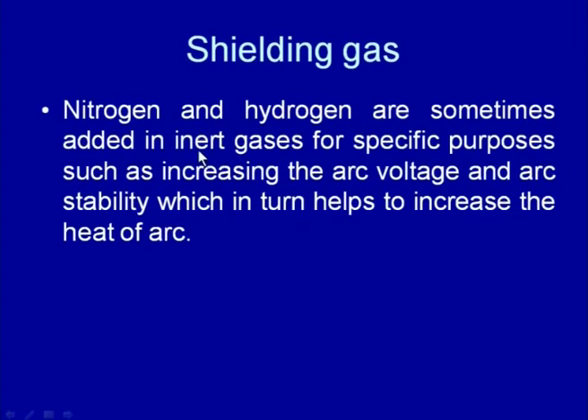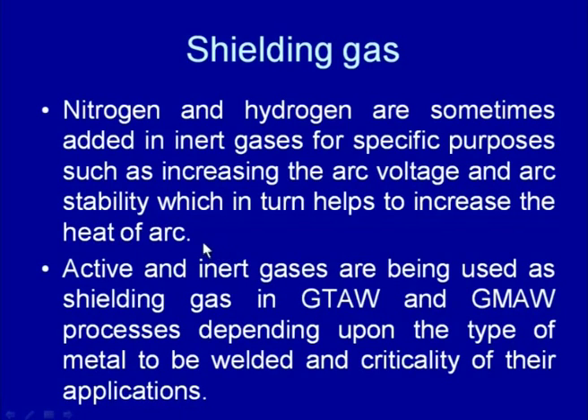Like when nitrogen and hydrogen are sometimes added with the inert gases for specific purposes such as increasing arc voltage and arc stability, which in turn helps in increasing the heat of the arc. So, addition of these two gases with inert gases like argon helps to have a higher arc voltage and better arc stability, which in turn increases the heat being generated by the arc, and this high heat generation helps in developing weld joints of thicker sheets at a higher speed.